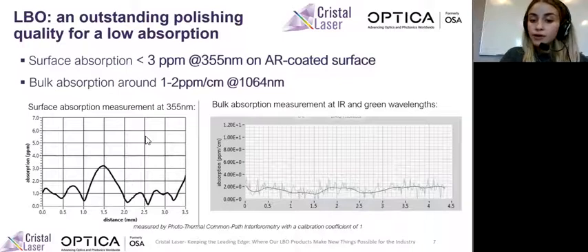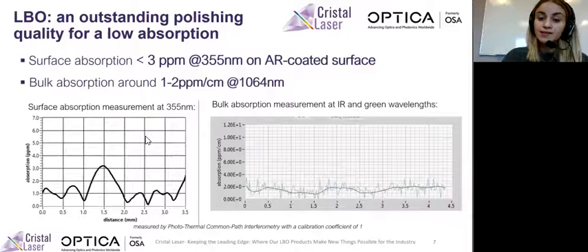Besides, at Cristal Laser, we also grow a low absorption crystal with a bulk absorption in the range of 1 or 2 ppm per centimeter at a wavelength of 1064 nanometers. This is also very important for the long-term UV operation, because it provides power stability to the laser, as the crystal will not heat up even when generating high UV power.